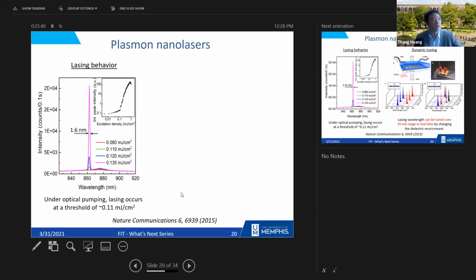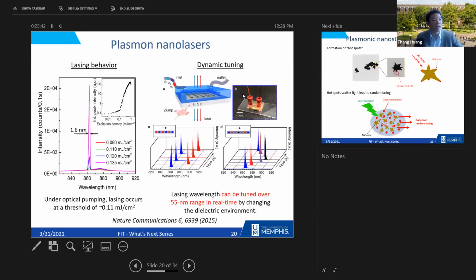In this case, we try to make a nano laser out of it. So this is an actual device. We put some dye molecules into that array of particles, and we hit that with a laser, and we see the signal coming out. We demonstrate the lasing behavior, and then this lasing signal can be tuned back and forth based on the dielectric environment that we put into the solution that covers the array. So basically, we can make a nano laser out of this plasmonic nanostructure.